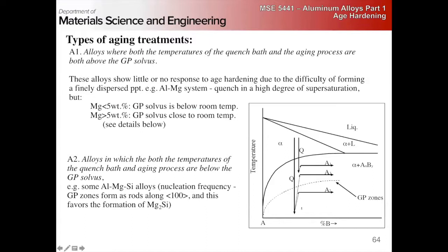So it's all a matter of temperature. If we're down here, say 130, we don't have nearly enough mobility, but we have a large driving force for nucleation. So we can nucleate the dispersion, and they'll be nucleated out small. If we're up here, well above the solvus, we're at a higher temperature. Remember, diffusivity is Arrhenius, so it's exponential with temperature.